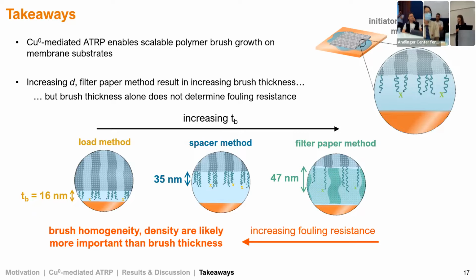Follow-up. Does that mean that the polymerization solution doesn't wet the fibers? It does wet the membranes. And we do actually see brush growth on both sides. I trimmed this talk down, so I'm only talking about the side we care about, which is the feed side. But the water or reaction solution will diffuse through the membrane and reach the other side. But we don't expect initiator sites on the pore walls. Okay, so we only expect brush growth from the surface. But the way I drew it is outward. It's possible that it's growing inward too, in my opinion.